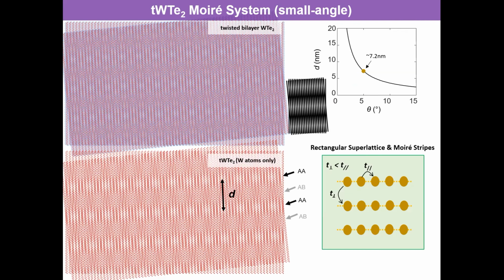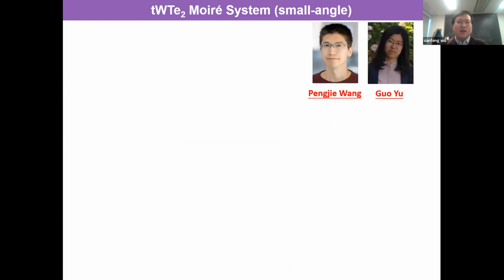So is there a special reason why you chose 5 degrees instead of a smaller or bigger angle? I will show you what happens at smaller angles too. So in general, between, I would say, 2 to 3 degrees and 10 degrees, the physics is similar, but they have some variations. I will show you. Okay. If you go to a large angle, the physics can be completely different. So, okay, there's no magic angle, so the small variation is fine.